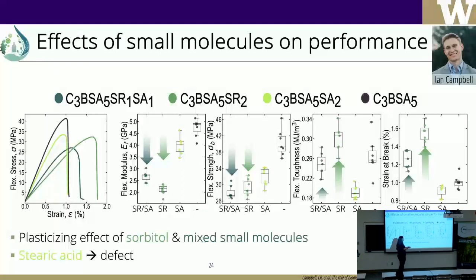We have an increase in our toughness at the expense of our strength and modulus. That's how you would introduce the effect that you would expect if you were to introduce an external plasticizer. We see the same or similar behavior in our mixed composite, but we don't see the same behavior with our stearic acid crystals, where you basically lose across the board. So you lose strength, you lose stiffness, and you lose extensibility.